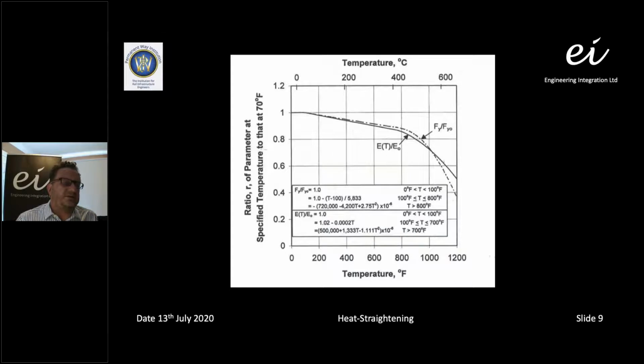We limit the critical temperature to 650 degrees C, because if we go above 650 degrees C, the crystalline structure of the steel starts to change, and it changes from body-centered crystalline structure to face-centered crystalline structure. That basically moves the carbon content around within the steelwork. If you then subsequently allow that steel to cool very quickly, some of that carbon can get trapped, and you get crystalline carbon concentrations in certain areas that cause the steelwork to become brittle. So we want to avoid that. That's why we heat progressively and we cool progressively. So that's what we're doing to the permissible stress.